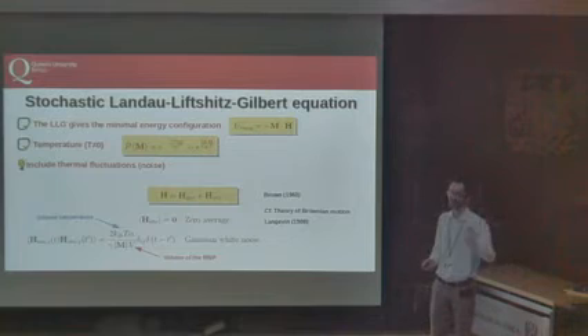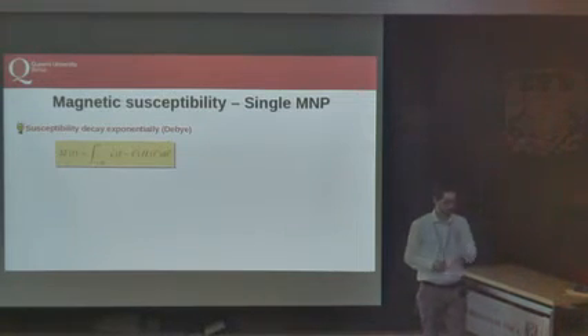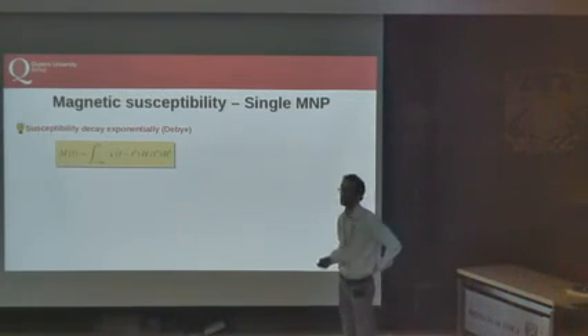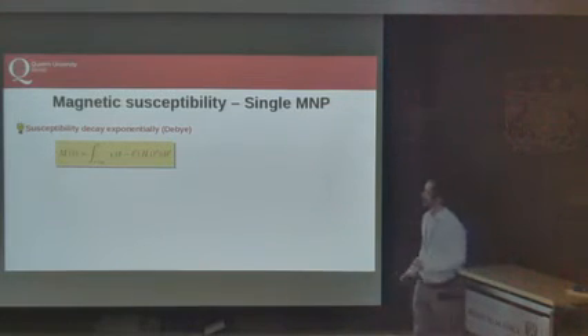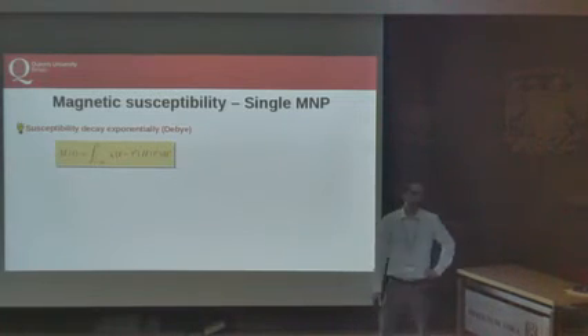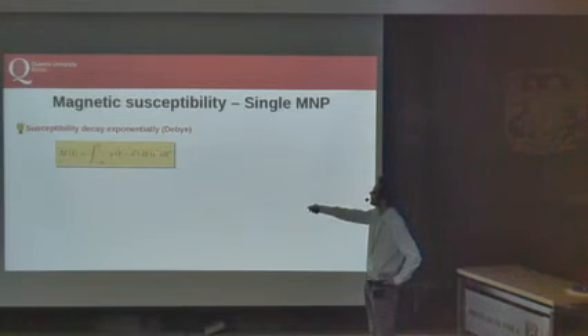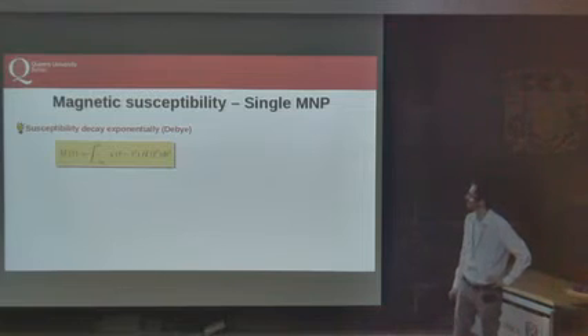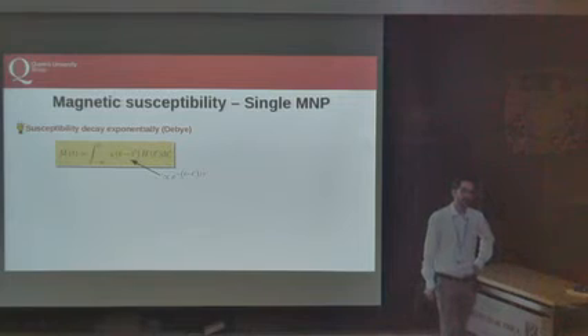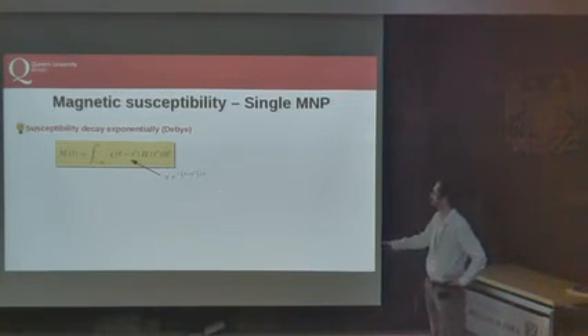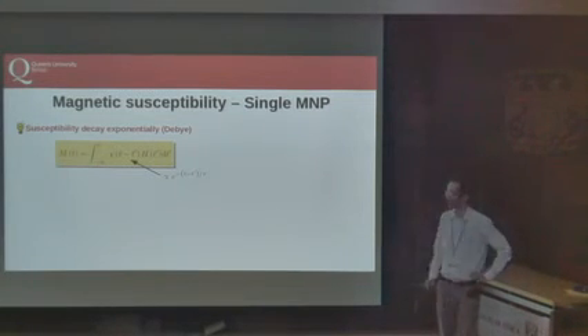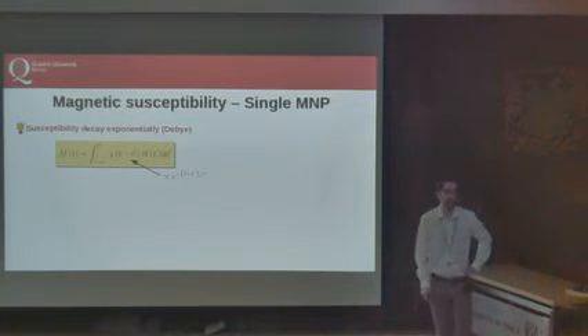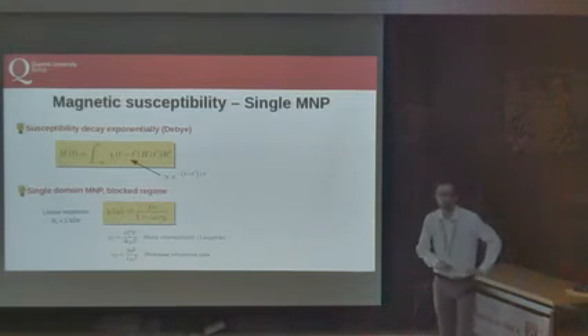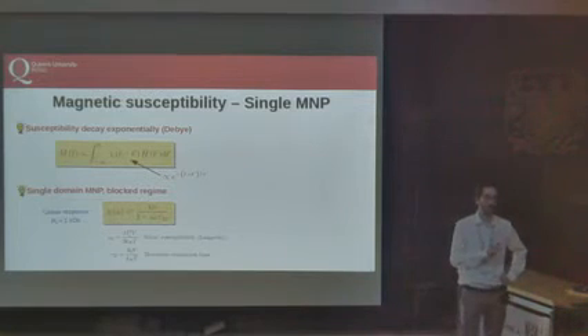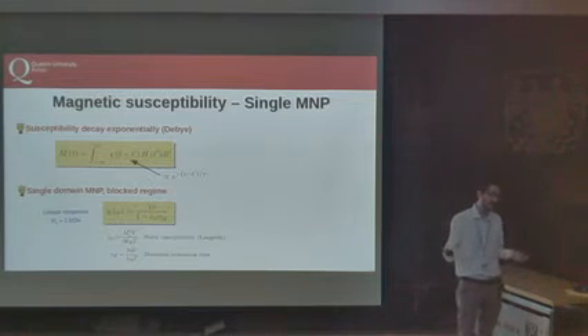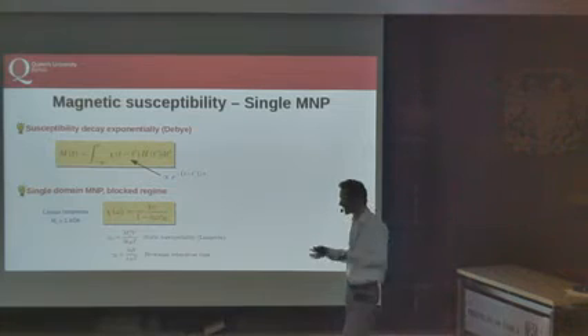So assuming that we have this numerical means of solution, what do we want to study? We want to study the so-called magnetic susceptibility of our magnetic colloids. The magnetic susceptibility chi, the volume susceptibility, is defined this way. It's the response function of the magnetization after you apply a magnetic field. It turns out that it can do several things, but there is an important component, at least in our case, which is an exponentially decaying component, at long time, with a characteristic decay time. In fact, there is even an exact solution for this system. It is exact, unfortunately, just for single magnetic nanoparticles. So we need to verify whether or not it applies to many magnetic nanoparticles.